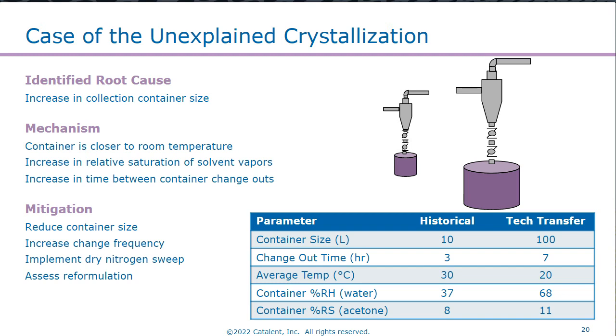So our materials in the collection container for our tech transfer batch would have had a much lower Tg relative to what we had seen historically. That lower Tg leads to plasticity, which can lead to API crystallization. The ways we mitigated this after we had identified this as the root cause were to reduce our container size, increase the frequency at which we change those out, and then a major one was the implementation of a dry nitrogen sweep. You can sweep the headspace of that collection container to remove that solvent vapor so that you're not plasticizing your SDD as it sits in that container.